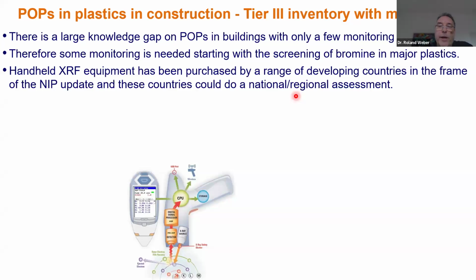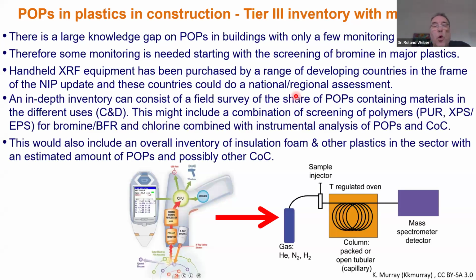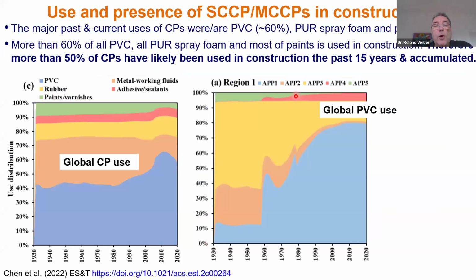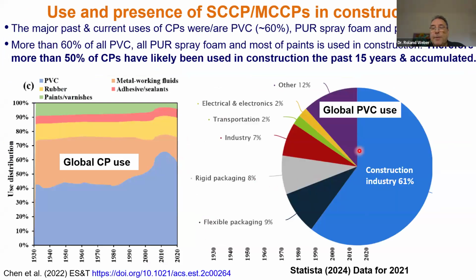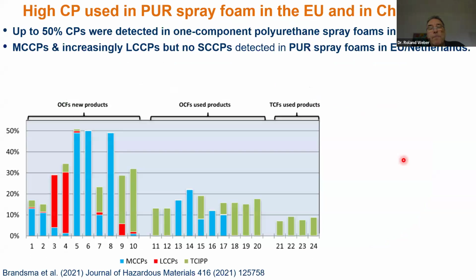Therefore, I recommend that countries with the capability do studies on POPs in plastics in the construction sector. What we know for sure is that short and medium chain chlorinated paraffins are the most relevant POPs for the sector. About 60% of the paraffins on average have gone into PVC, and about 60% of all PVC goes to construction. Here it is especially the plasticized, soft PVC, not the rigid PVC for window frames. It is rather for flooring and other materials where we have chlorinated paraffins in construction.